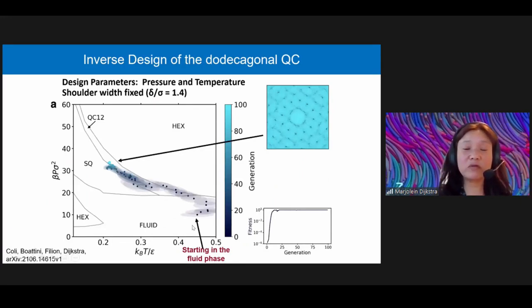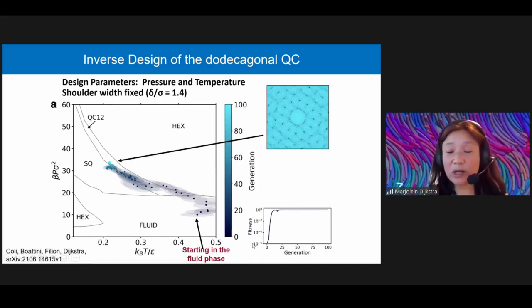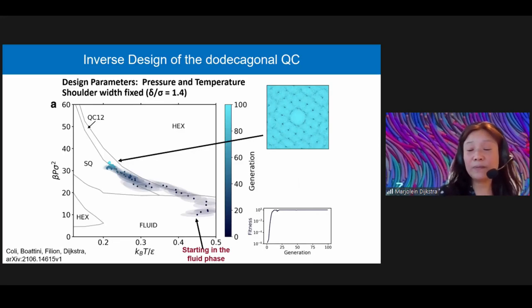We can start, for instance, with our evolutionary strategy algorithm in the fluid phase, with this bivariate Gaussian distribution. We take n samples from this bivariate Gaussian distribution, perform simulations there, and then we update it in such a way that it moves towards higher and higher fitness values. The fitness is shown here on the right at the bottom. It goes from a fitness value of 10 to the minus 6, and then it increases over the different configurations towards 1 in about 10 generations.